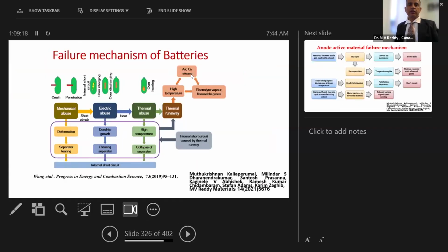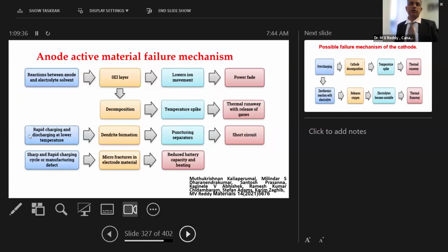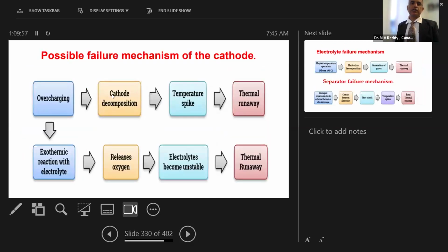We have to understand the failure mechanisms of batteries. We have to see whether it is mechanical abuse, electrical abuse, or thermal abuse, which can lead to thermal runaway due to high temperature, dendritic growth, electrical abuse, deformation, or separator issues. These are all very important. On the anode side, lithium dendrite formation due to fast charging leads to short circuits. That's why the BMS protocol doesn't allow charging very fast, due to the issues with graphite. Similarly, with cathodes, overcharging leads to thermal runaway: an exothermic reaction with the electrolyte, oxygen release, and sometimes a large volume variation.